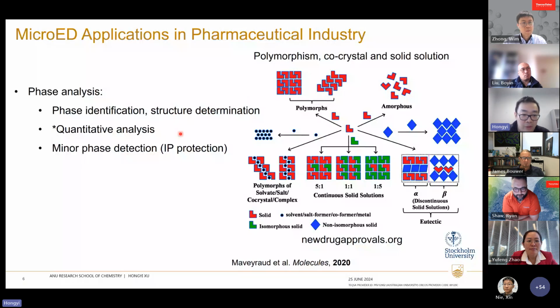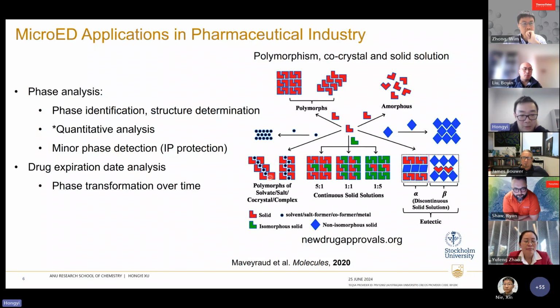So powder diffraction is probably still better to do this task for now. But later, with high throughput and automation, I think we can achieve this also with electron diffraction. And then we can also detect minor phases in the powder. So this is very useful for IP protection. And then we can look at drug expiration date because we can look at the same powder over time and then see how the polymorphs are changing and transforming between each other. So one phase transforms into a different phase over time.